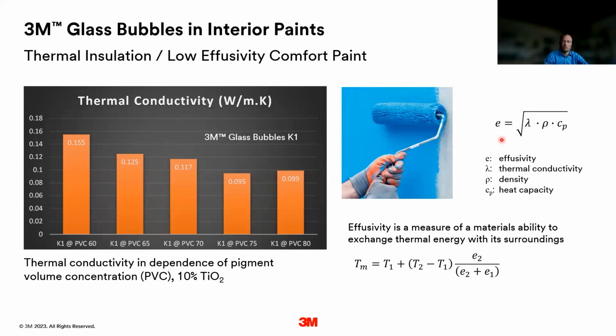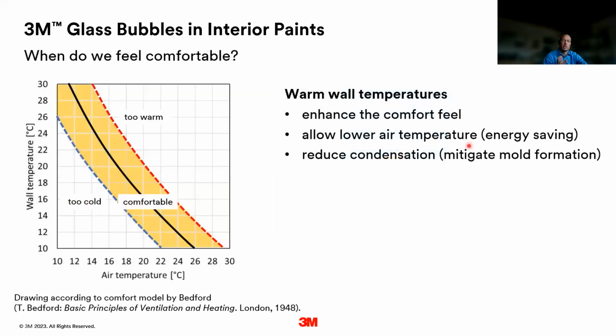So that's the reason why in winter, concrete feels cold and wood feels warm. That's thermal effusivity. And glass bubbles, in the formulation, decrease the thermal conductivity, they decrease the density, which gives us low heat capacity as well, and therefore low effusivity. So it's a warm touch. If you touch a wall painted with glass bubble paint, it feels warmer. And also, if you measure the temperature, due to the insulation effect, the wall temperature can be a little warmer, not just 1 degree C, maybe 2.